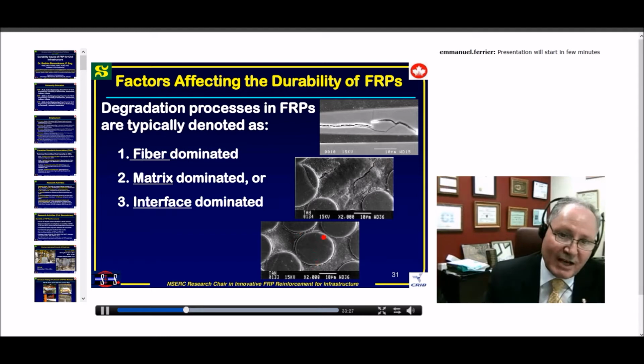And when you have this debonding and delamination, of course, you are losing one of the main criteria, if you can call it this way, to act as a composite material. When you are losing the interface, the whole system is not really acting as a composite, and you can have a decrease in strength, because you don't have any stress transfer between the fibers.